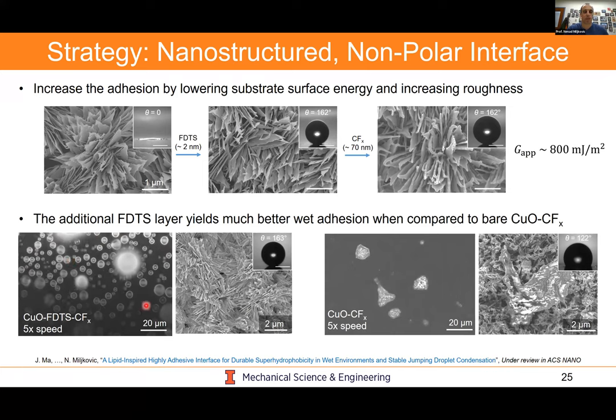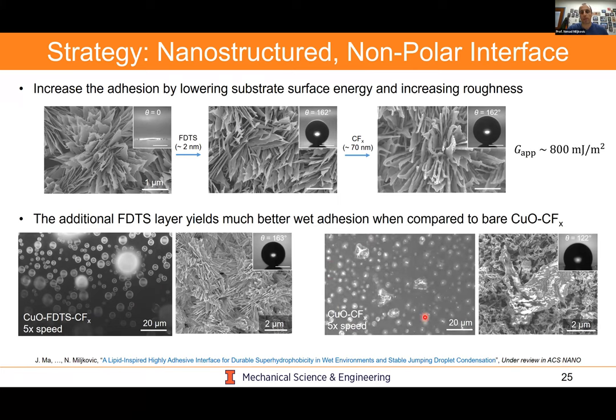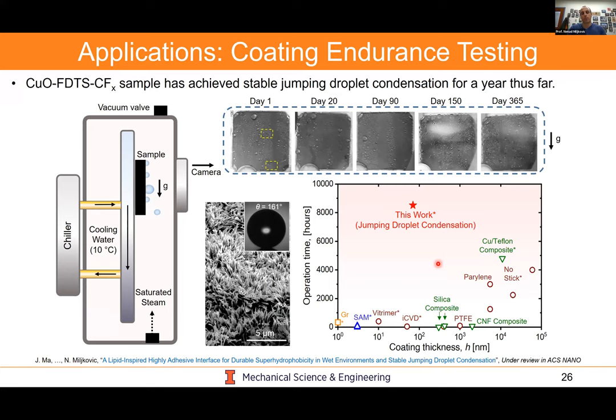I apologize for the sound in the video. And then here, this is what happens on the coating, which only has the polymer on it. You could see that it degrades quite badly. It doesn't work very well. And so to really prove this works, we actually put this experiment, and it's been ongoing for more than a year. You could see here, 365 days, we have stable droplet jumping.